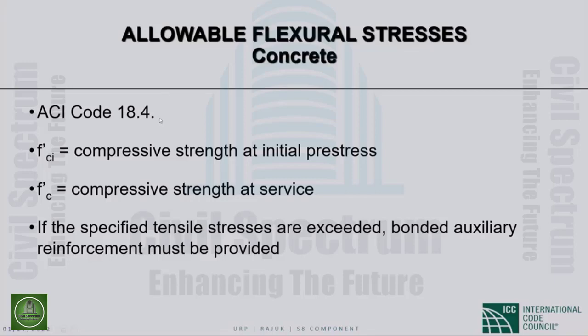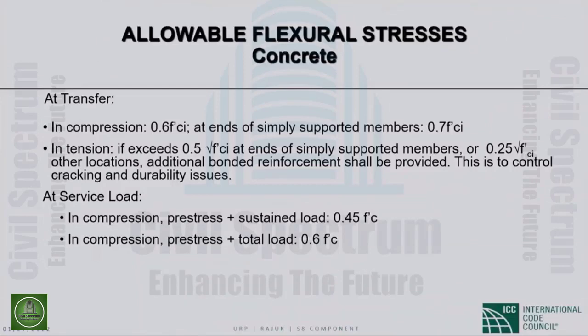So ACI gives us, as I mentioned, the limit. Very important, okay? These kinds of stress limits are not in the regular reinforced concrete part of the ACI code. They are only in pre-stressing because pre-stressing can drastically change the stress situation depending on the support condition and the eccentricity. So if the specified stresses are exceeded, ACI asks us to use bonded auxiliary reinforcement. We must provide additional steel reinforcement, which is mild steel, which is supposed to supplement the pre-stressing steel. And it's supposed to address all these unintended stresses that we need to control in pre-stressed members. So these are the stress limits.